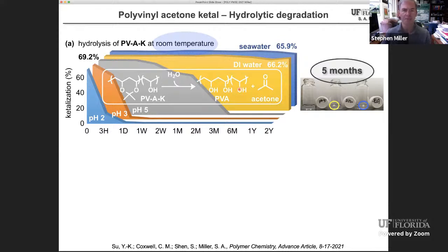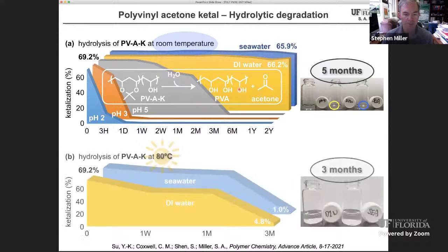So rather than doing the 3-year experiment and waiting longer to publish, I asked my student, Yukai, well, why don't we just heat these? Okay, we'll simulate time in both deionized water and seawater. We'll simulate the passage of time by heating them. And we just decided to heat them to 80 degrees. So they're in a hot water bath at about 80 degrees. And what we see is that after 3 months, both in seawater and deionized water, they're almost completely hydrolyzed, certainly to the point where you don't see them anymore. The little plastic chunks are gone. If there is any ketalization, it's not impacting the water solubility of these materials. They seem to be water soluble, so they're no longer visible, right?